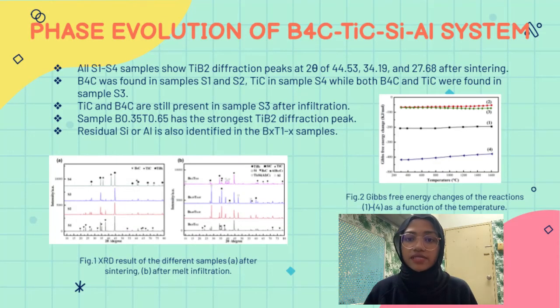All S1 to S4 samples show titanium diboride diffraction peaks at 2 theta of 44.53, 34.19 and 27.68 after sintering. Boron carbide was found in samples S1 and S2, titanium carbide in sample S4, while both boron carbide and titanium carbide were found in sample S3, indicating that their incomplete interaction during sintering could continue under the liquid path of aluminium-silicon melt.